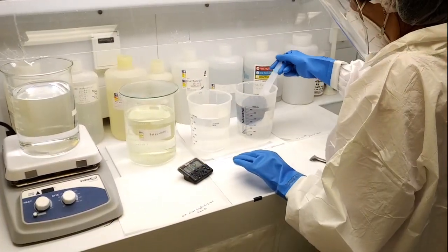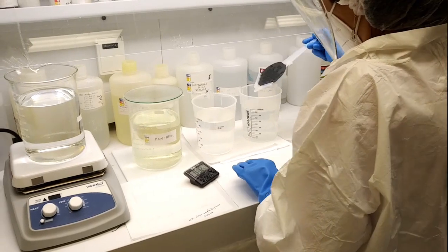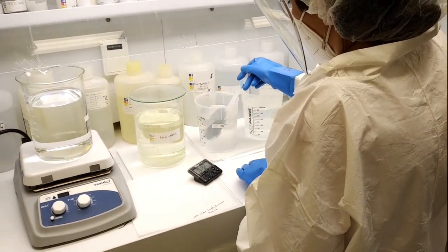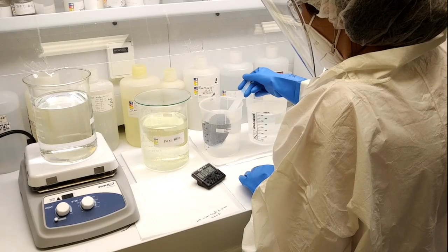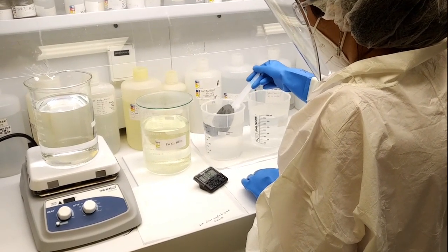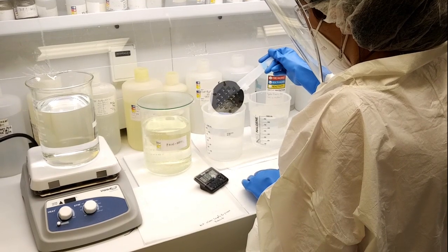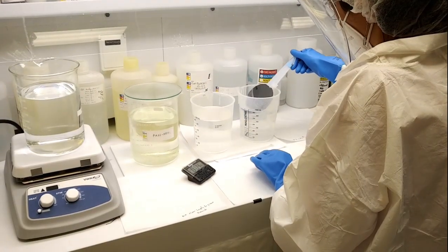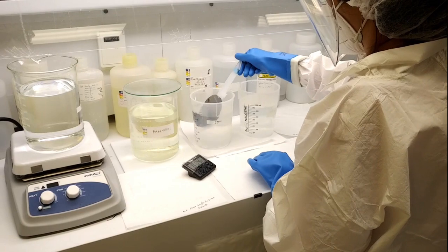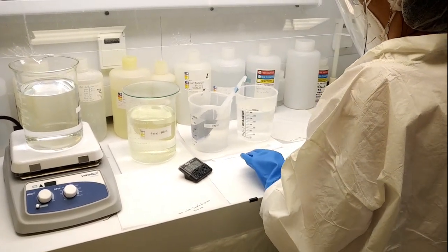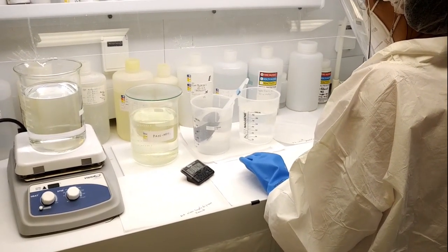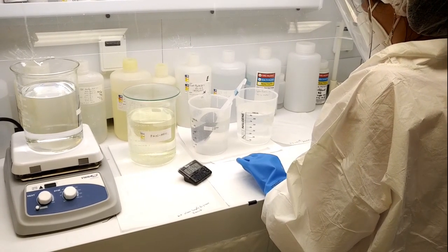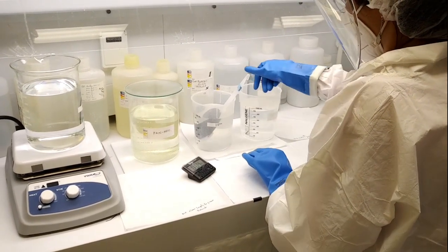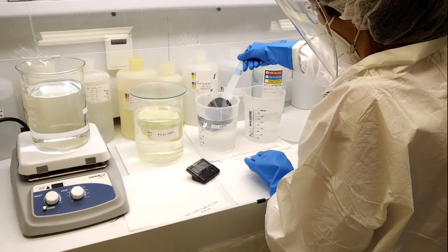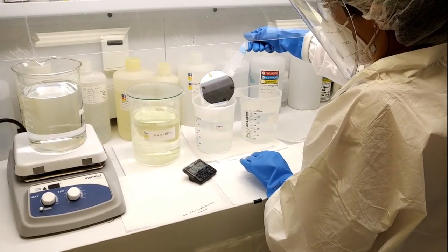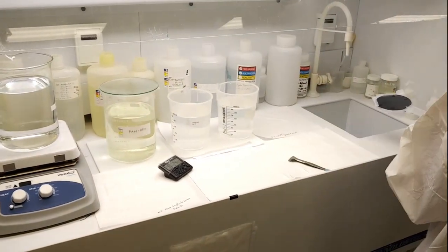With the mask marks protected, the wafer is dipped in buffered HF solution until the oxide mask is completely removed. The length of time is monitored to track the removal process. When the oxide mask is removed, the wafer is fully hydrophobic. The process can be carefully monitored to ensure the oxide is completely removed. The MOSFET is about half finished now with the doped source and drain regions. The next steps are the gate oxide formation and finally metal deposition to create the metal gate, source, and drain contacts.